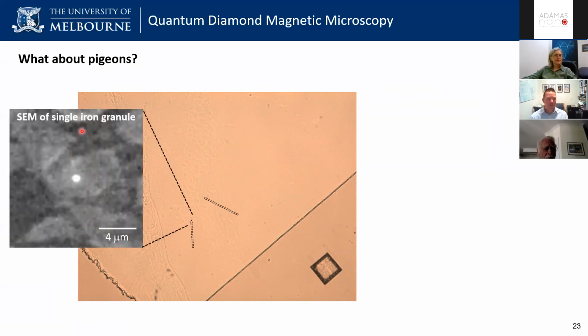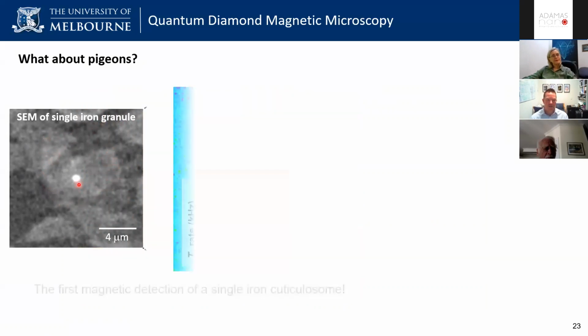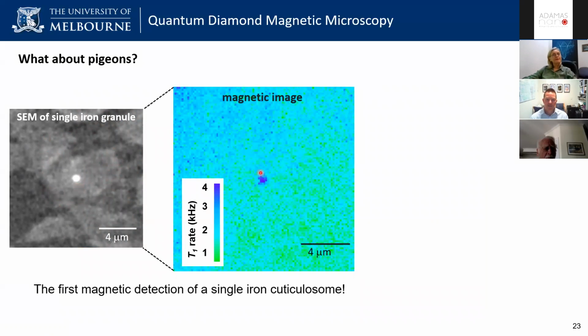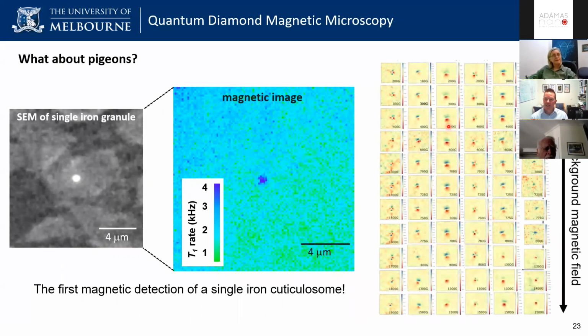And so here is an SEM of one of these particles. So you can see the single cell with the iron cuticulosome there. And then when we do our T1 imaging, we're able to show that we can indeed detect a fluctuating signal from one of these particles within the inner ear of a pigeon. And then we went and did a more systematic study looking at lots of different particles in the inner ears of pigeons. Here we're using ODMR to actually image the stray magnetic field under the presence of various background magnetic fields.